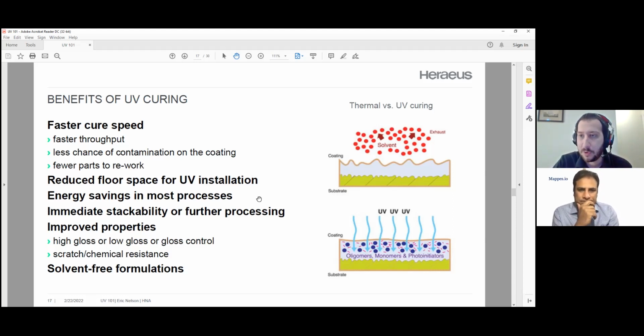We see on the right here an example of the sorts of chemistries and the differences between the chemistries. So on the top, we have a thermal chemistry where basically you have this coating that's kept as a liquid inside of a solvent. The solvent evaporates off as an exhaust, and what's left behind is a dry coating. Right. The UV process, you have a mix of monomers and oligomers. A monomer is a single chain of a polymer, right? It's a single chain of a plastic. An oligomer could be multiple chains, and then a photoinitiator is a UV reactive material. Okay. And by mixing all these together, when you shine UV onto it, the photoinitiator will react and kick off a chemical reaction. And I'll get a little bit more into how photoinitiators work in an upcoming slide.